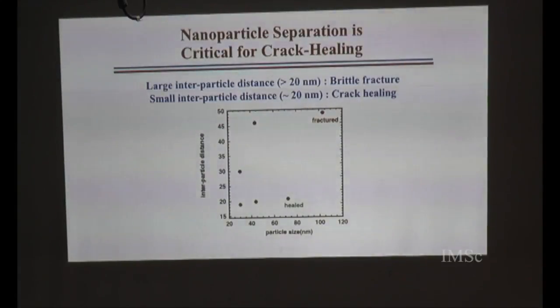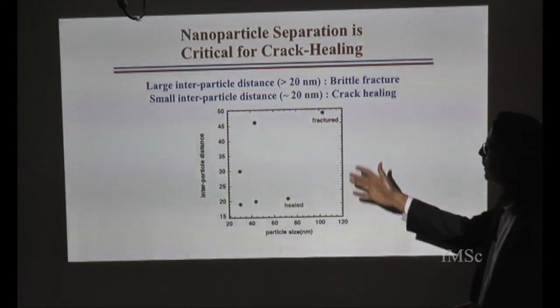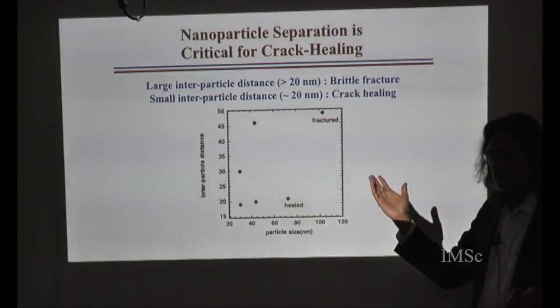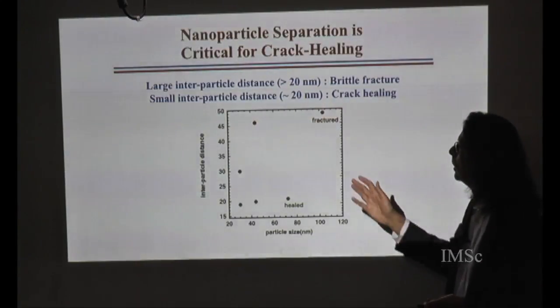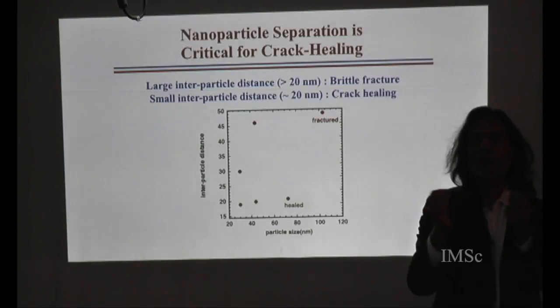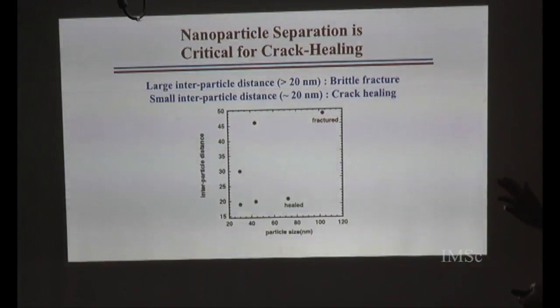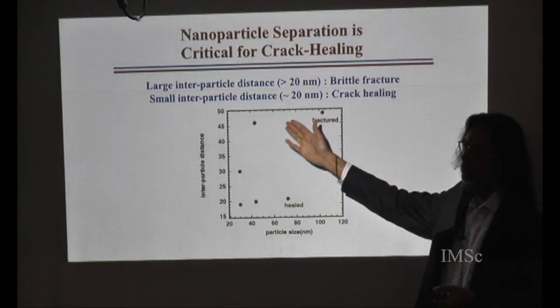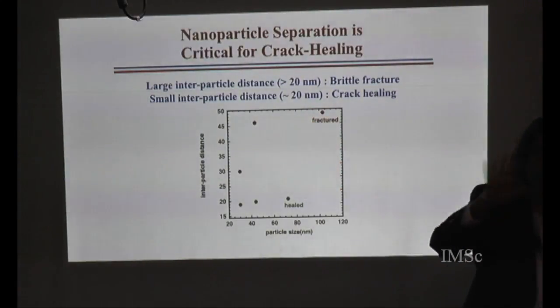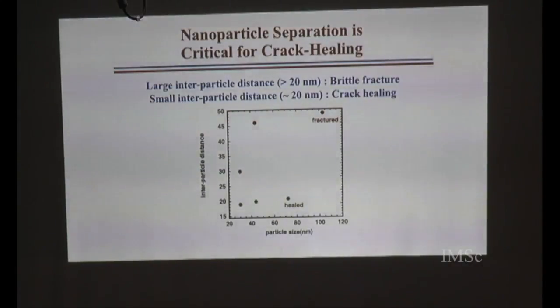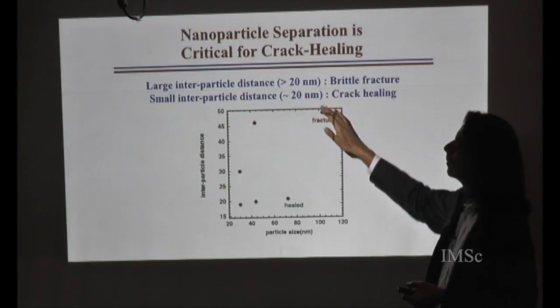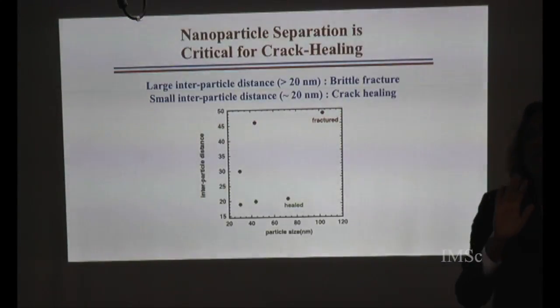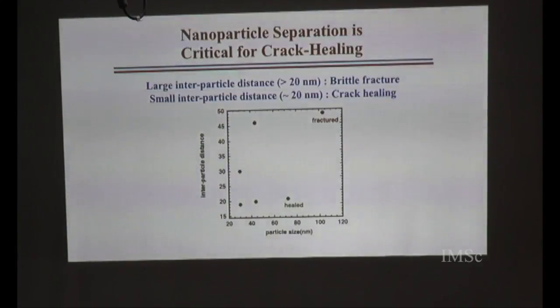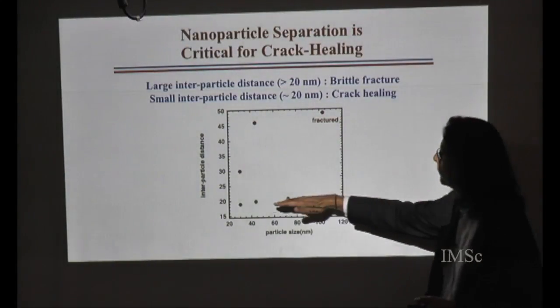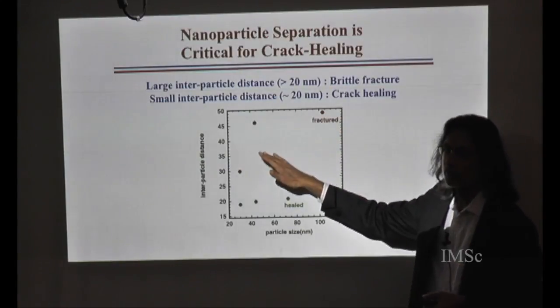So the first, sort of crude observation is, when we look at crack healing in this system, we find, and it's not surprising, that if the distance between nanoparticles is large, greater than 20 nanometers, the system tends to fracture. In the alumina matrix, the crack goes through, it fractures. However, if the interparticle distance is on the order of 20 nanometers or less, then we see crack healing. This is what it is showing: these samples were healed, these samples fractured.